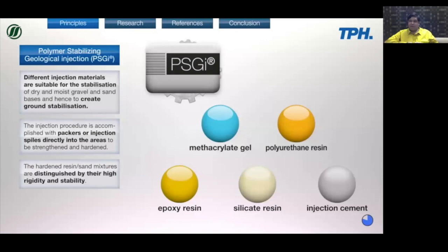Epoxy resins we are very well aware of. They have been used, but again, they are very rigid, very brittle systems. So unless you really need that kind of strengthening, we don't mostly look at it for ground stabilization application. It finds much more use in repairs and rehabilitation, where you use it with concrete to inject cracks in concrete. Now, silicate resins is another new kind of material that has come to the fore.